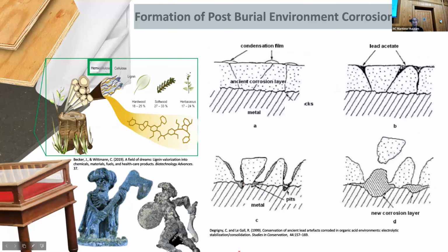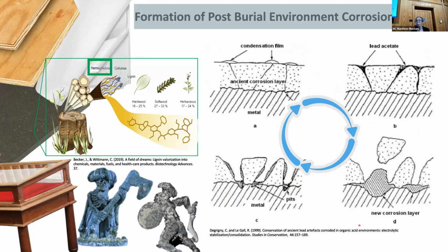So you get these little pits and reservoirs that form that then just sort of collect moisture and collect those acid vapors inside of them, which then can create exponential types of corrosion. So then you get these new corrosion layers that form often underneath the old ones that often result in losing that protective crust and any information they might contain as well. And this is often cyclical. So this is kind of self-sustaining. So this is something that we definitely keep an eye on. And these are also products that we want to remove.